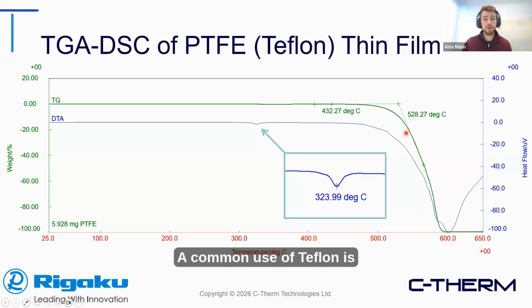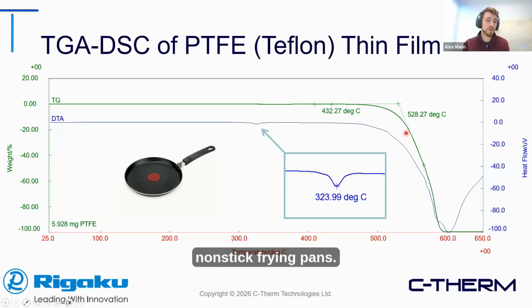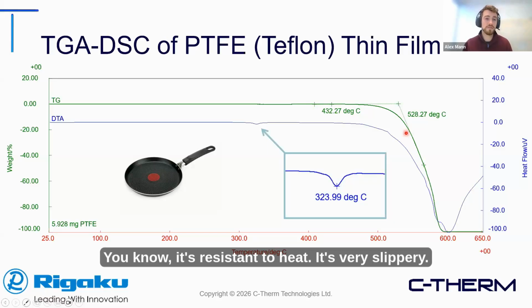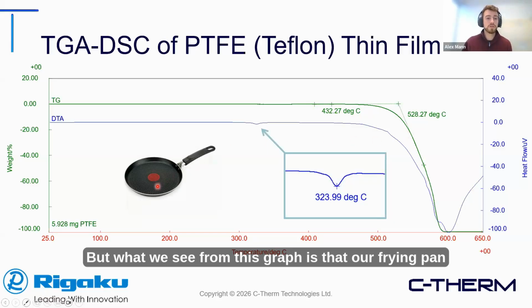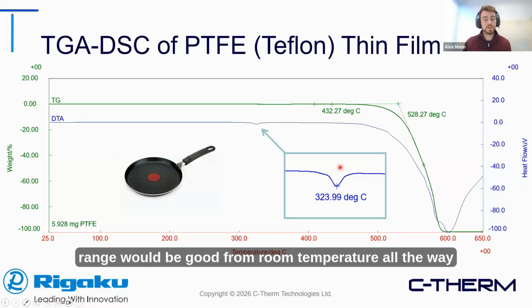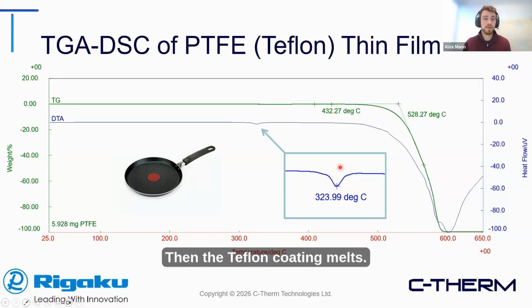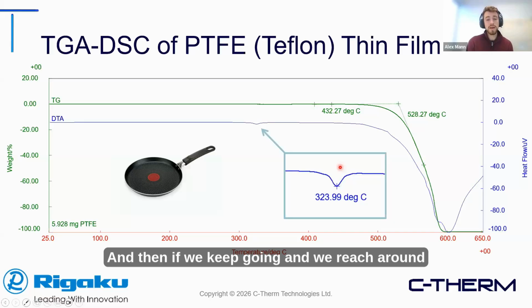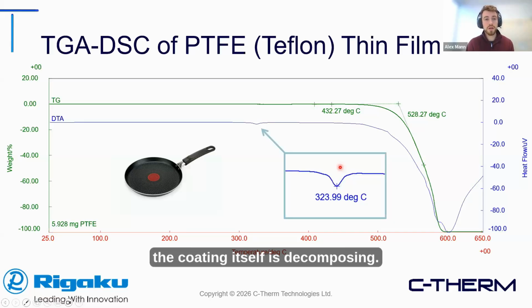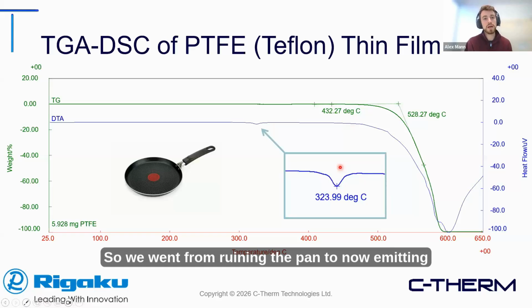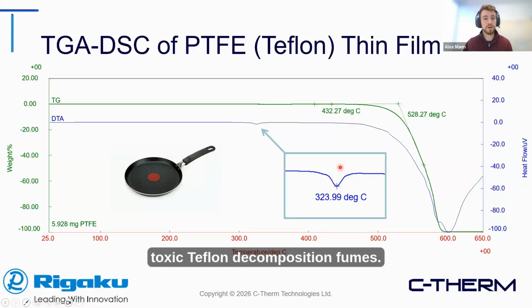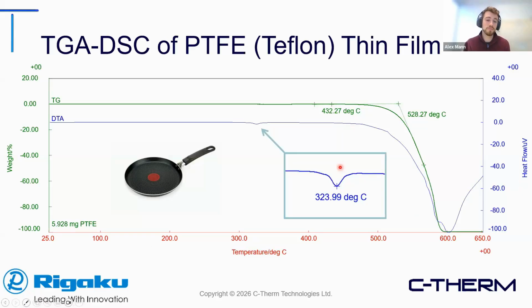A common use of Teflon is nonstick frying pans. It's resistant to heat, it's very slippery. But what we see from this graph is that our frying pan range would be good from room temperature all the way up to around 330. Then the Teflon coating melts, so we have effectively damaged our pan. And then if we keep going and we reach around 430, now all of a sudden the coating itself is decomposing. So we went from ruining the pan to now emitting toxic Teflon decomposition fumes.